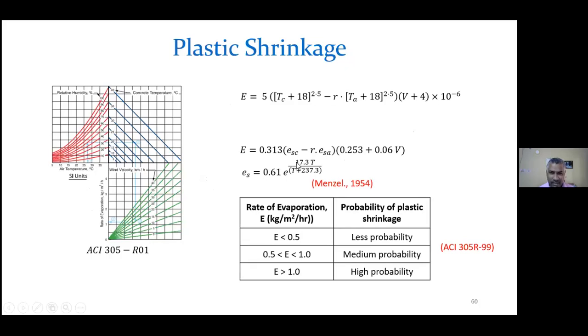Some formulations are already available to find out the evaporation rate, and it depends on temperature of concrete, relative humidity, temperature of the atmosphere, and the wind velocity. This is as per the code ACI 305R, and there are some other equations with these same parameters. So if we can measure the concrete temperature, atmospheric temperature, relative humidity, and wind velocity, we can easily measure the rate of evaporation. The code says if the rate of evaporation is less than 0.5, there is no probability of plastic shrinkage to occur. If the evaporation rate is 0.5 to 1, there is a medium probability. If it is greater than 1 kg per meter square per hour, which is the unit for evaporation rate, then there is a high probability.